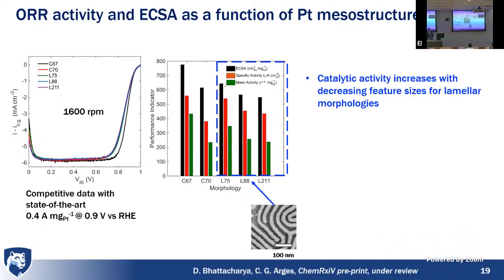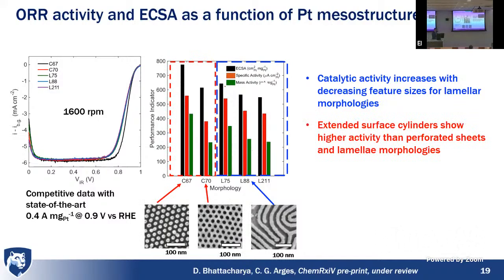What I want to point you to first in this lamella structure are the degrees of polymerization. This is the molecular weight of the copolymer, so this is a higher molecular weight. This might be something like 40-some nanometers, and this might be like 20 nanometers. When we make the width smaller, we get higher mass activities, right? That would say higher surface area, better performance. In the cylinder cases, these are our standing cylinders, and these are our perforated structures. This is where we're taking advantage of block copolymer lithography. We put down the platinum, and these extended surface supports gave the highest mass activity.